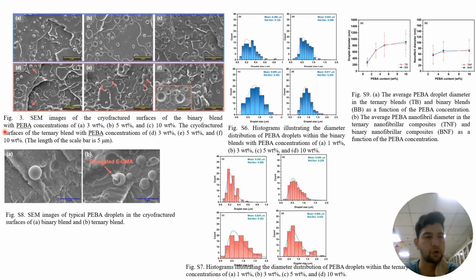Furthermore, look at the morphology, the SEM images. These are SEM images of the fracture surface of the binary blend. Binary blend means two components, PMMA and PEBA, containing 3%, 5% and 10% PEBA. The result shows this is the matrix, it is PMMA, and the droplets are PEBA. In all concentrations the dispersion is good. It shows a uniform dispersion of PEBA droplets throughout the continuous PMMA matrix.